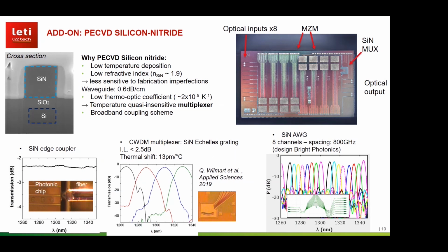Another add-on or building block which is very important for Datacom is silicon nitride. So in the MASSTART project, we use silicon nitride for two reasons. The first is for multiplexers. The multiplexer AWG is in silicon nitride, and we can take advantage of the low thermo-optic coefficient, which means that the multiplexer has a low sensitivity to temperature.